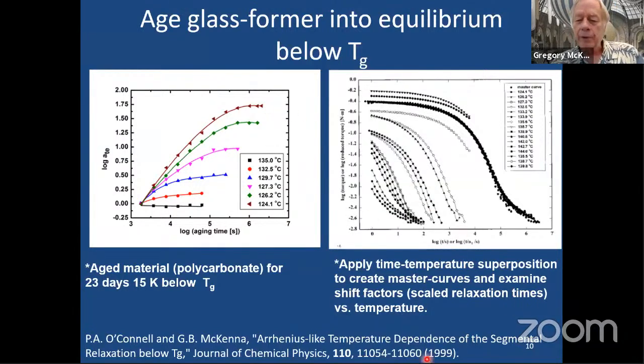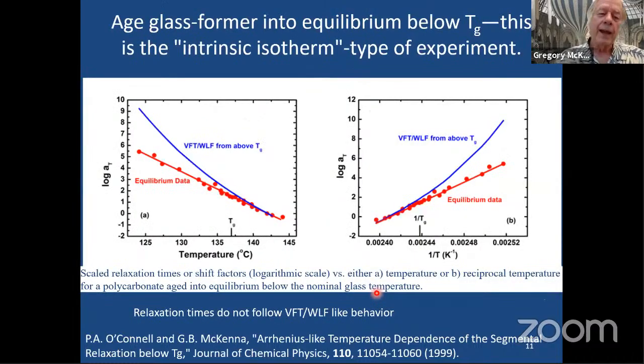Then we applied time-temperature superposition to create master curves for all the scaled relaxation times versus temperature. And then we could ask, what happens to the scaled relaxation time, the shift factor, as a function of temperature or as a function of 1/T? What we see is a pretty big deviation from the Vogel-Fulcher behavior. To us, it seems fairly clear that there's a problem with at least the VFT extrapolation.